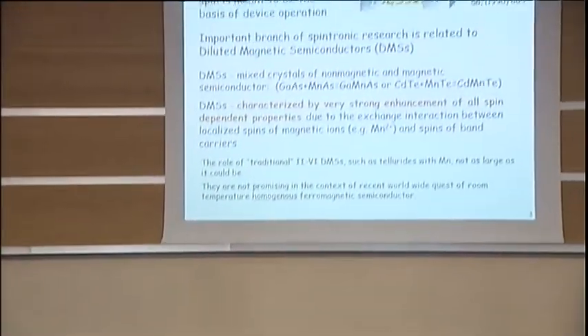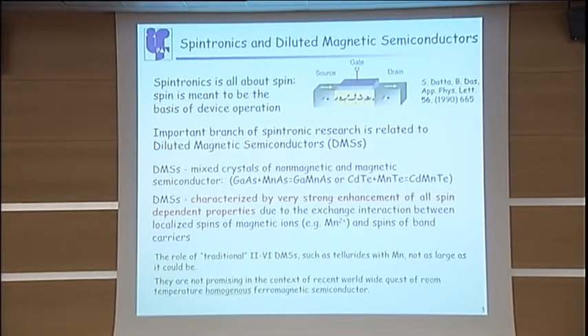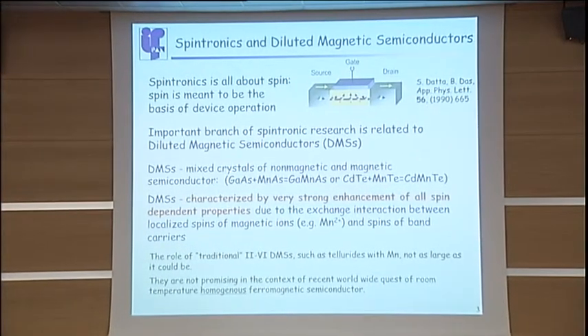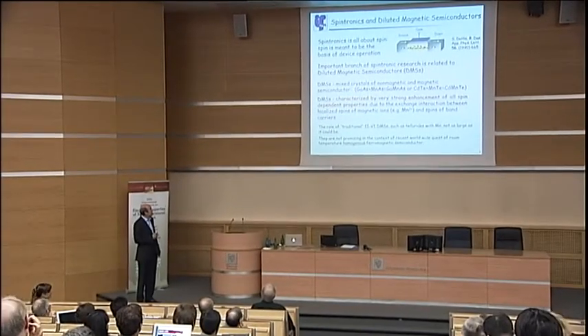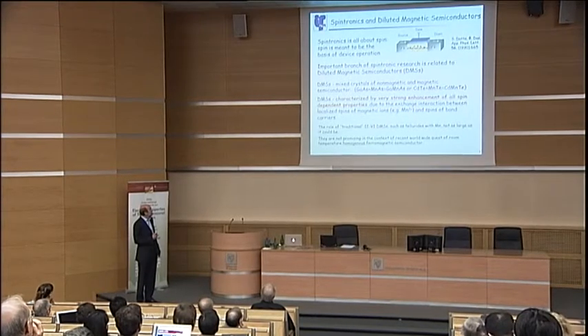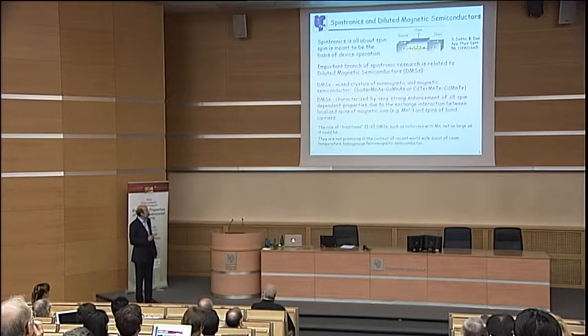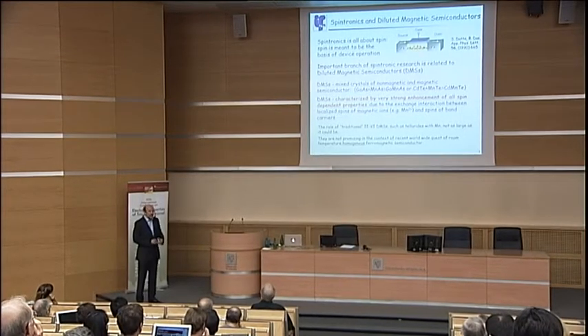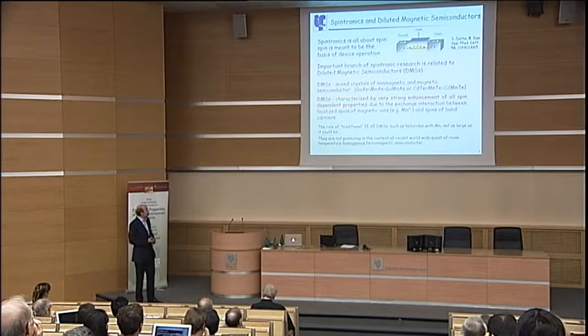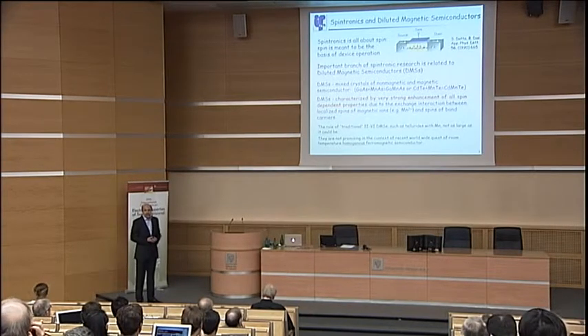Of course, we all know that spintronics is all about the spin, because the spin is meant to be the basis of device operations. And therefore, an important branch of spintronic research is related to diluted magnetic semiconductors, which are mixed crystals of non-magnetic and magnetic semiconductors, with cadmium manganese telluride or gallium manganese arsenide being very well-known examples. And the reason for the interest in diluted magnetic semiconductors from the point of view of spintronics is that those materials are characterized by very strong enhancement of all spin-dependent properties. And that is due to the exchange interaction between localized spins of magnetic ions and spins of band carriers.